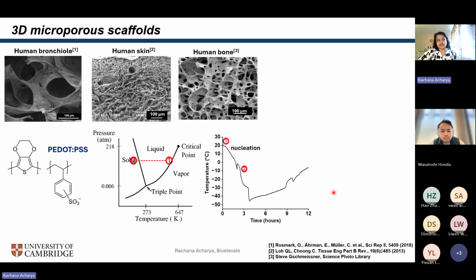When we reduce the temperature in the system, the water part of the dispersion is going to freeze. So it's going to nucleate and form ice crystals, and you're going to have a liquid to solid transition. At this point, if I reduce the pressure in my system, these ice crystals directly go from the solid phase to the vapor phase. So they sublimate out. And this is where I can increase my temperature and bring it back to room temperature. And this is the drying phase.